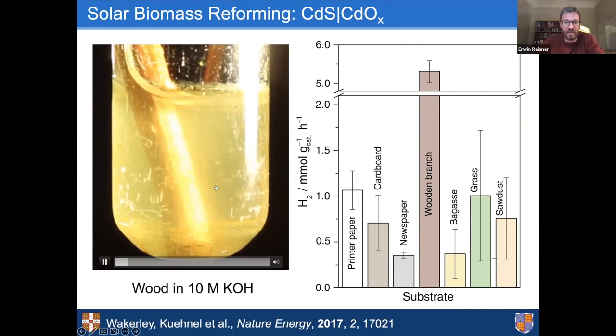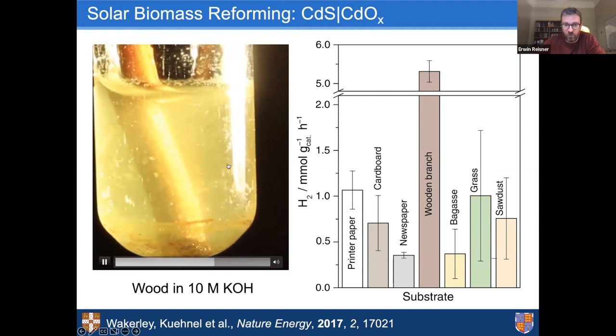And as the yellow takes up the light and approaches the wood, it starts actually oxidizing the wood, so oxidizing the wood to break down into organic acids. And at the same time, it starts using the electrons to generate hydrogen. So this vigorous bubble formation here is from hydrogen evolution on the wood stem, if you like. So it's quite an efficient system. So we were quite excited about this result.